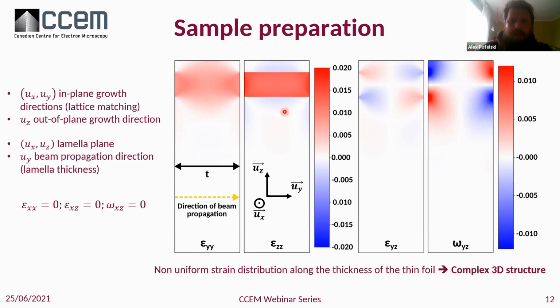So as a consequence, there will be a response in the out of plane direction, because we don't have a fully in-plane growth here. And so you can see that there is some contrast variation. That is, we don't have something that is uniform here. Regarding shear and rotation, we will still have some impact, but we're going to neglect that for the moment. We're just going to focus on this out of plane